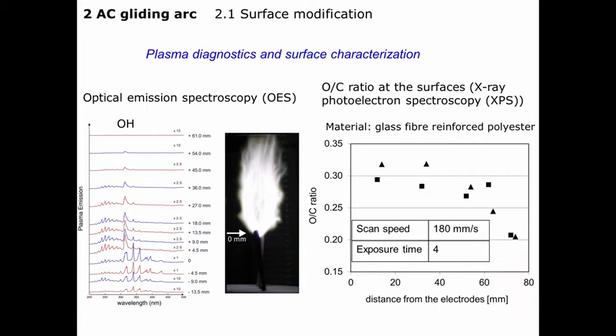Before that, I made a small characterization of the plasma by detecting optical emission from the plasma. Optical emission spectroscopy is a very powerful technique without destroying the plasma at all, detecting reactive species which can emit photons in the detectable range. There are many emissions, but among all, we noticed the emission of excited state OH, a bit longer than 307 and 8, 9, something. This emission is detected up to around 6 centimeters above the electrode. And I must tell you that OH is a very oxidative agent, and it is said to be even stronger than chlorine. It's a very, very strong agent.